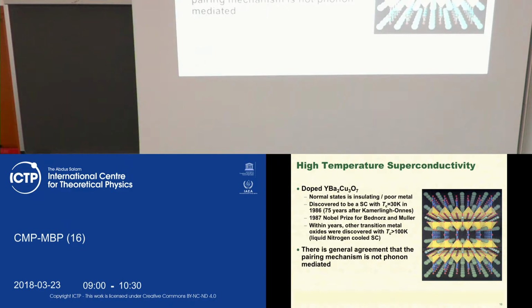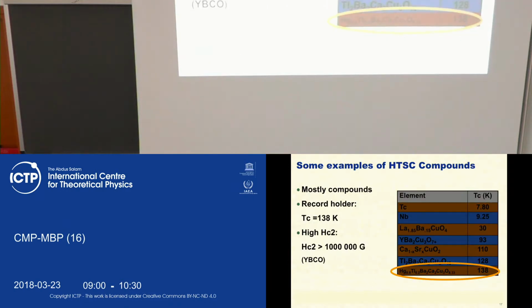And since there is not yet an understanding of the mechanism, there is no real understanding of which system one needs to look for. Of course, in the discovery of the superconductors, it was clear that superconductivity should be found in the family of these copper oxides. So people started to use other copper oxide compounds like lanthanum copper oxide, mercury-based copper oxide. But most of these things were done just empirically, by checking a parent compound, checking similar compounds in the hope that there might be higher temperature superconductivity, and sometimes it happened. However, there is no strategy, and this is another challenge: there should be a strategy in the search and in the hunt for new high temperature superconductors.